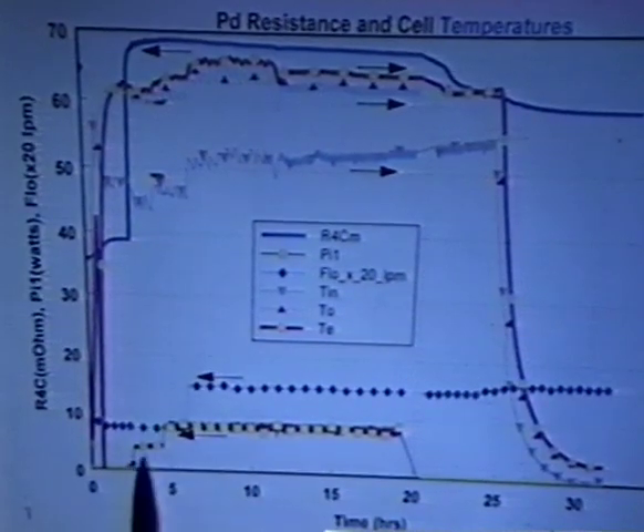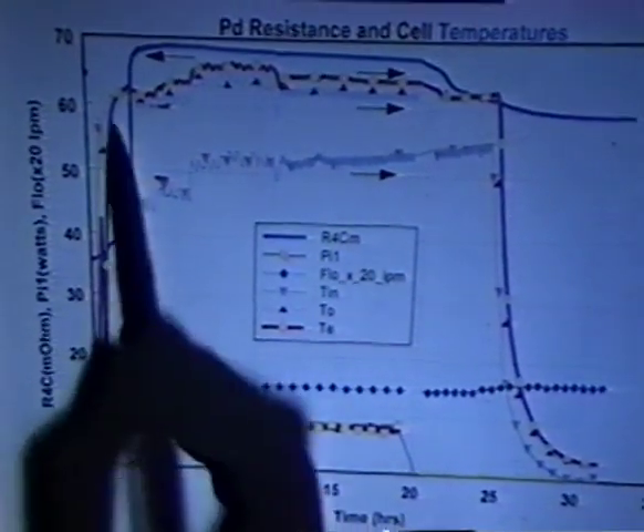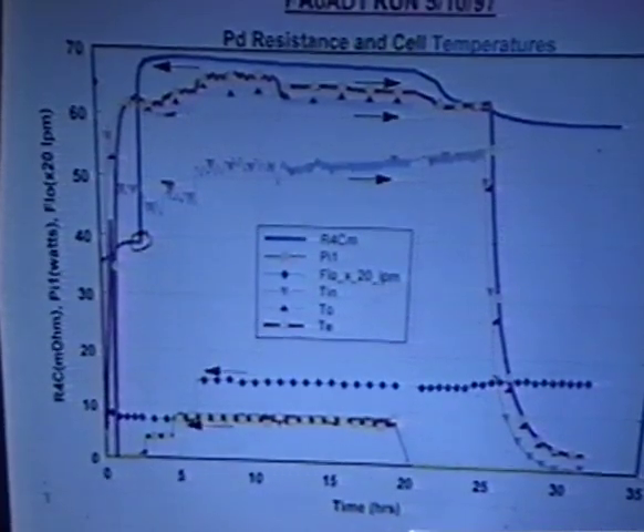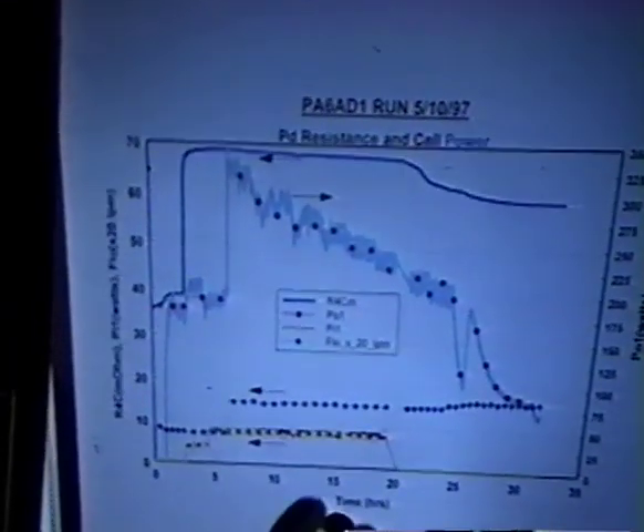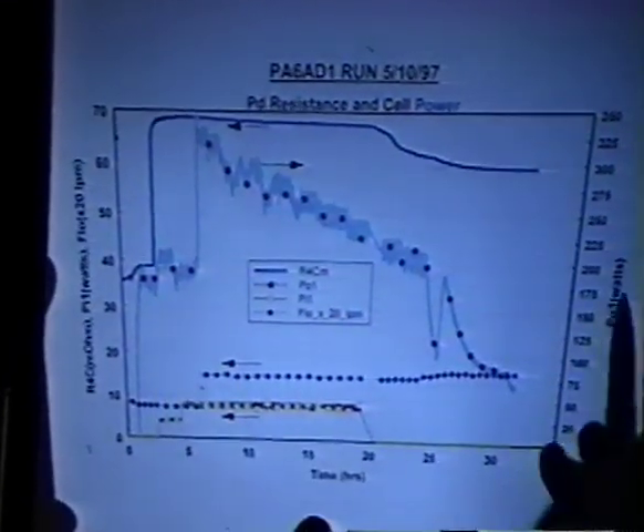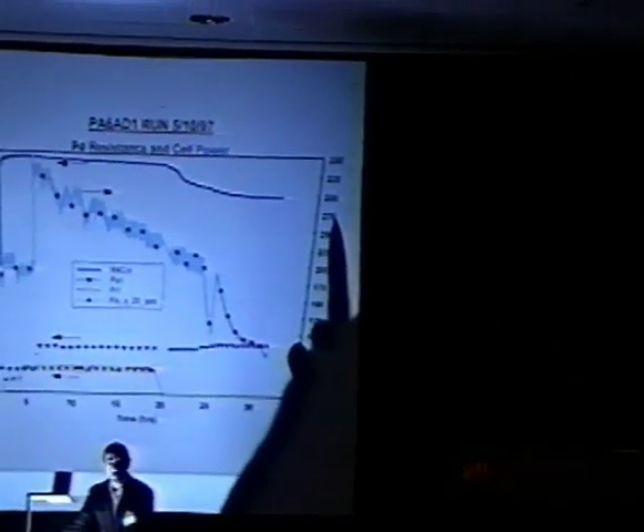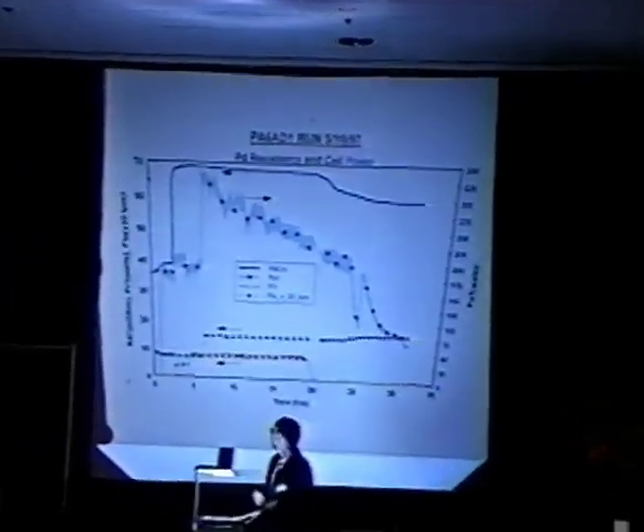And it does make a small change, and you'll see when this current was first turned on is when the palladium began charging. So the resistance went up. But the power actually shows up before that. In fact, I thought I'd show you the blow up. And again, if you calculate the power levels for this particular system over this whole period, they're on the order of 200 and 250 watts over that range.